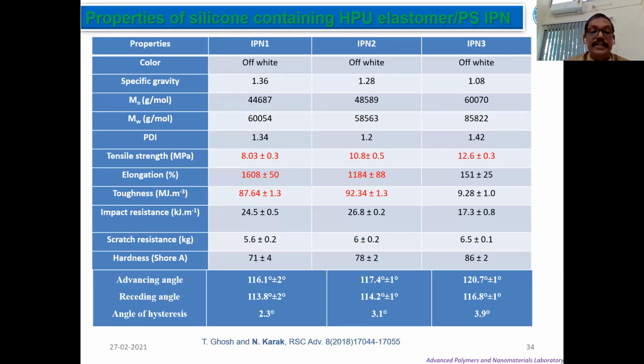Though the angle of hysteresis is a little bit increased, overall hydrophobicity becomes very high, up to 120 degrees contact angle, and also the mechanical strength is increased. However, the elongation or flexibility reduced drastically.